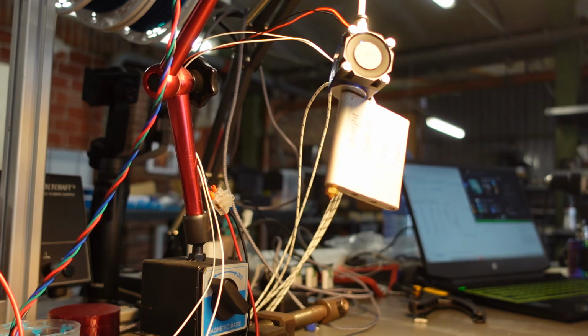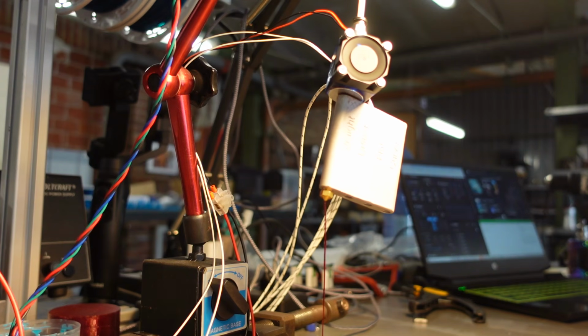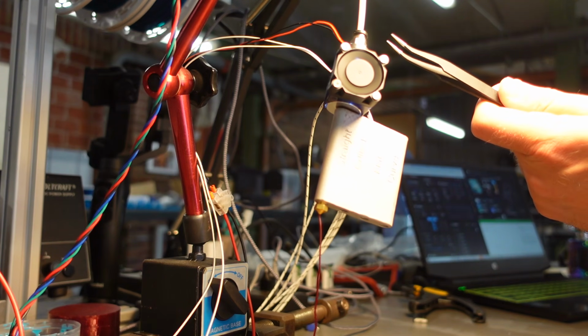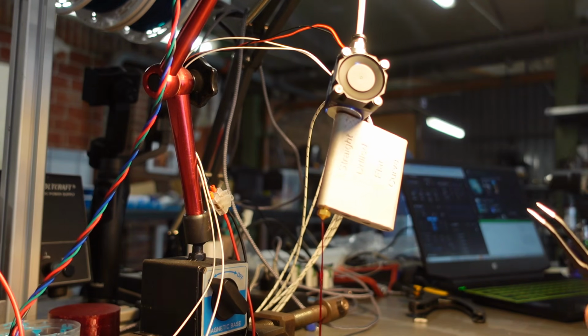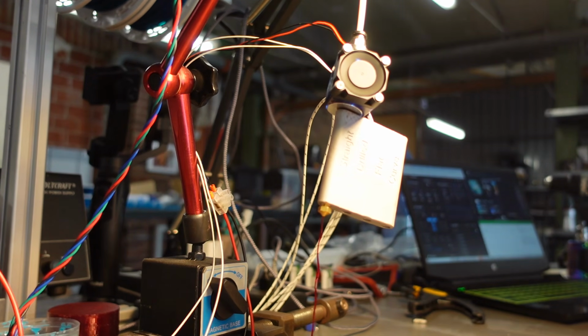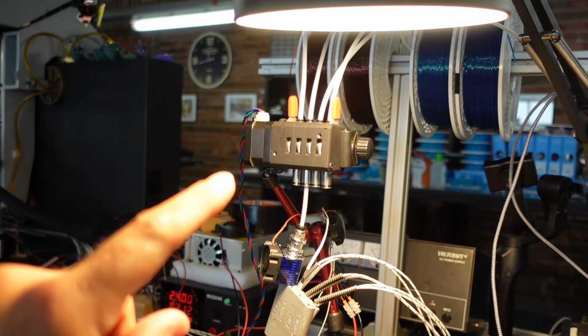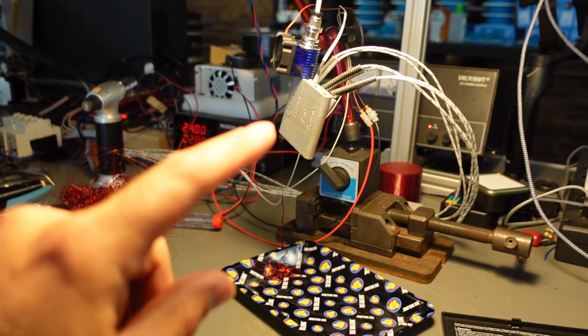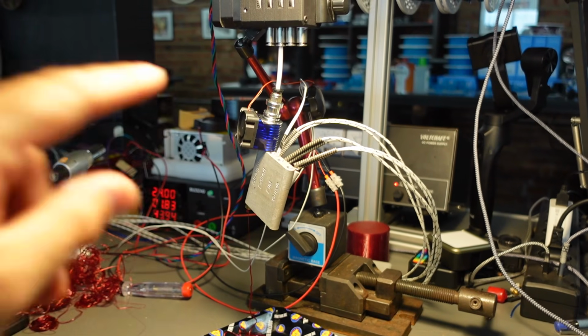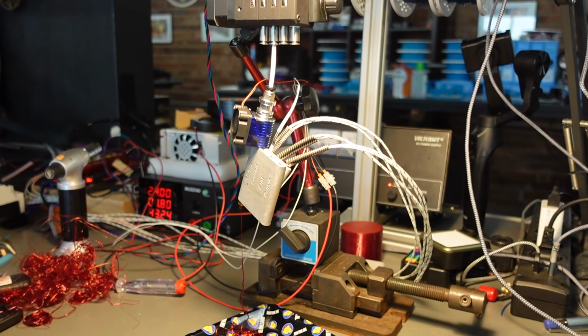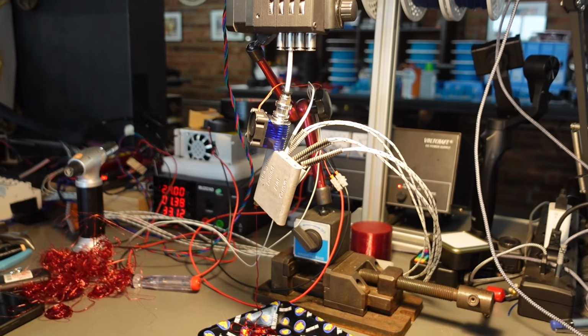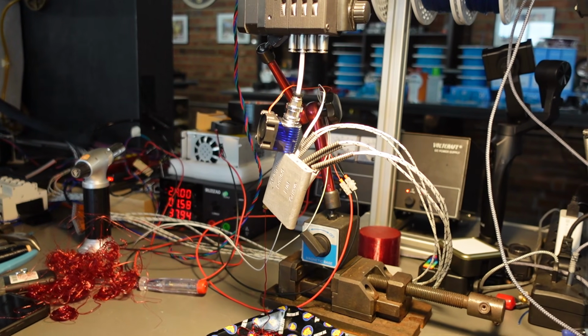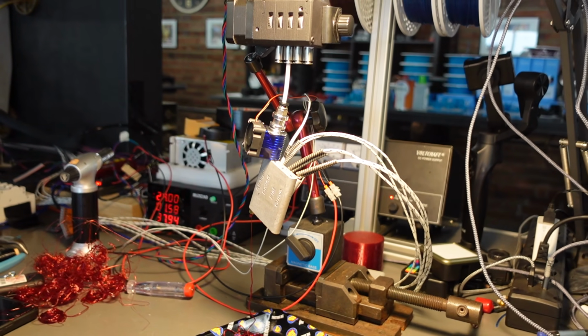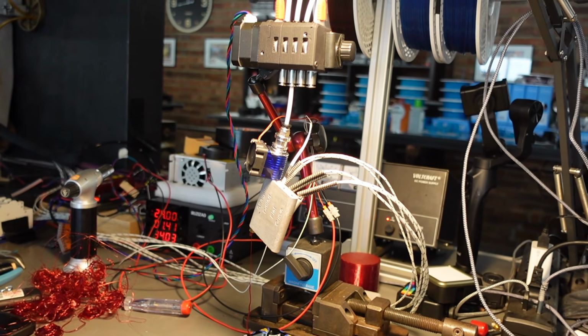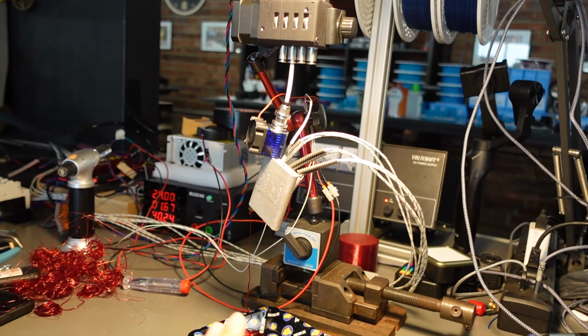Last move was 80 cubic millimeters, let's do 85, and you'll see that this will go. Yeah, you can see the PTFE tube isn't even able to hold the... I'm gonna abort here. We got a mixture of skipped steps from the extruder, and then also the PTFE coupling isn't able to keep up. So it's a clear indication that our forces are too high here. And this is something we don't want to have when we do standard 3D printing. We want to stay in the range where the system is comfortable.